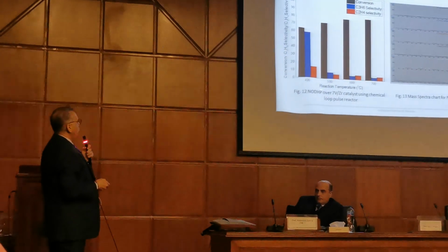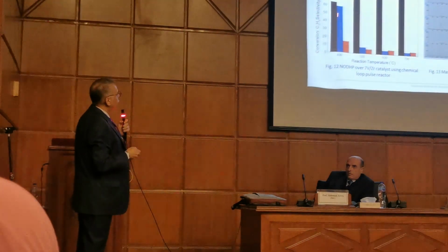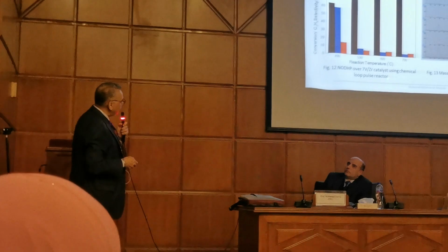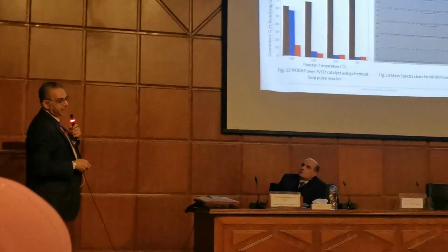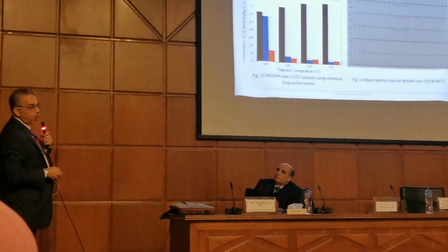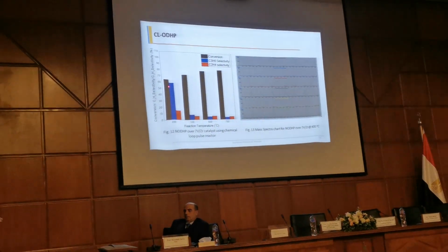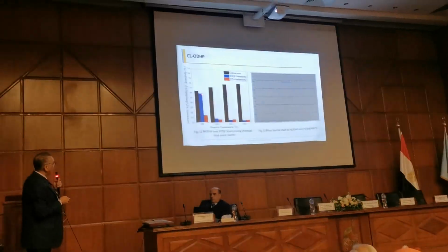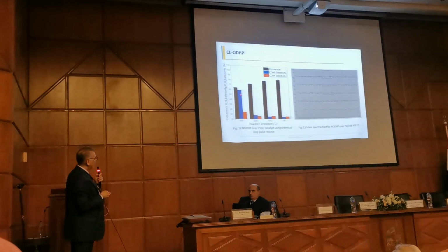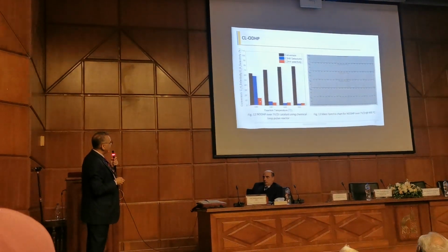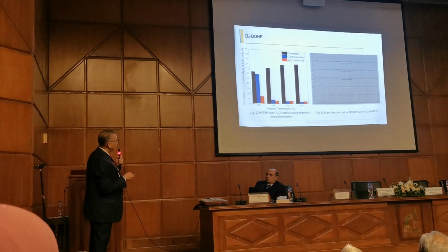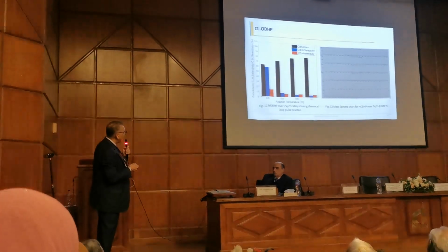So we have to use a suitable temperature of 400 degrees centigrade. There is no thermal cracking, only catalytic cracking now. At this temperature, we found very good conversion and very high selectivity towards propylene production. Of course, you have some selectivity for ethylene, but at high temperature we don't care, because we are concentrating on the temperature where there is no thermal cracking at all.